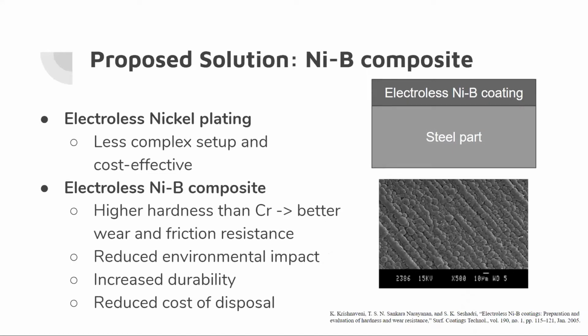Thus, to solve this issue, we will introduce the electroless nickel plating due to its less complex setup to coat complex structures, and it is also a very cost-effective technique. We will dope this electroless nickel material with boron to increase its hardness. And it has been shown that the electroless nickel-boron material has a cauliflower-like microstructure, which you can see here, and this will result in better wear and friction resistance. In addition, the environmental impact is reduced, and it will lead to also an increased durability, as well as less disposal costs due to recycling of the bath.